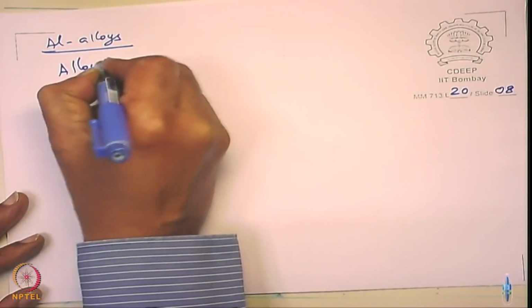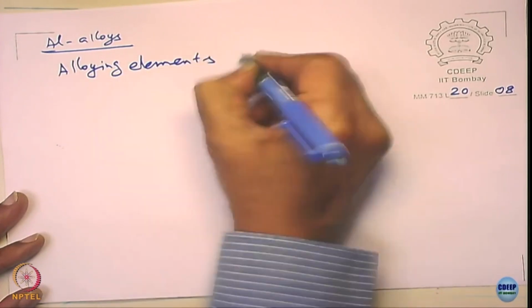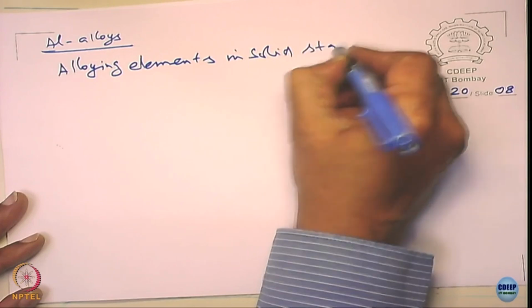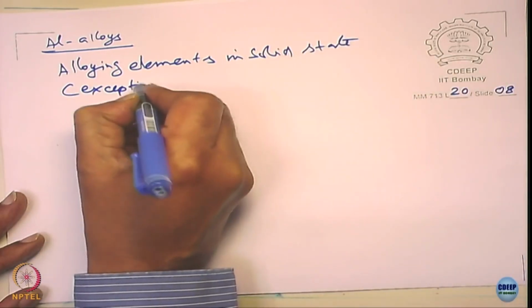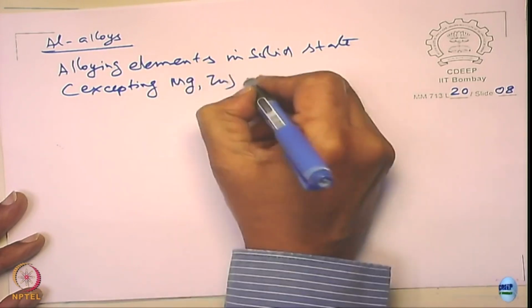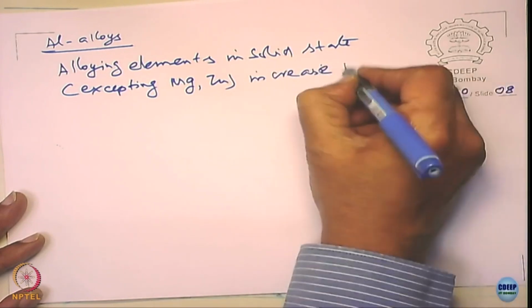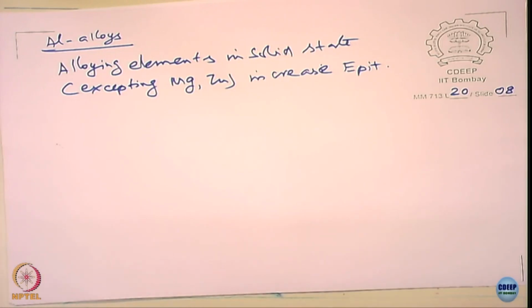alloying elements in solid state, that is excepting magnesium and zinc, increase EPIT. So, they are generally good, but you do not make aluminum alloys generally with the elements in the solid solution. You always want to have precipitates to increase the strength performance actually, but from a scientific point of view, you can add so many elements like molybdenum, tungsten, chromium and a host of elements. If you can put them in the solid solution, you will find a very significant improvement in the pitting resistance of these alloys actually.